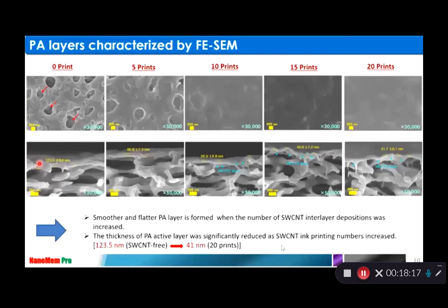Initially, you remember we targeted 10 nanometer of the polyamide, which will give a very high permeance from the previous year's literature. Then when we had zero printing, you can see the 125 nanometer of polyamide layer we identified, and at 5 prints, 95 started decreasing. When you increase the cycles of your printing, finally 41 nanometer, even though we were not able to achieve the 10 nanometer polyamide thin layer. However, definitely we reduced from 120 nanometer to 41 nanometer. And then we look at the overall performance, whether this shows better rejection and water flux.